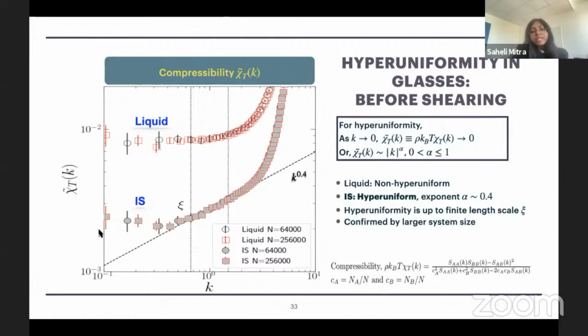Interestingly, at very low wave vectors, we see that the plot deviates from the hyperuniform power law fit, and that is because the system does have finite compressibility. We confirm that this deviation is indeed a property of the system, and it is not merely because we have a smaller system size. We confirm this by going from 64,000 particles to 256,000 particles, and we see the exact same trend. That means we can now see the inherent structures obtained from the high temperature, high density liquid to be hyperuniform up to finite length scales.